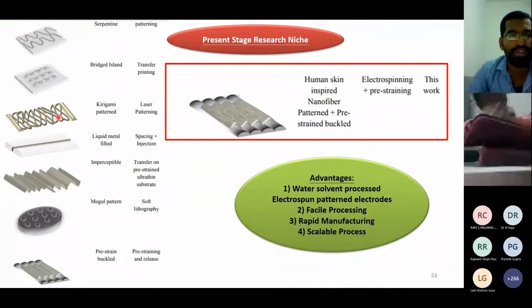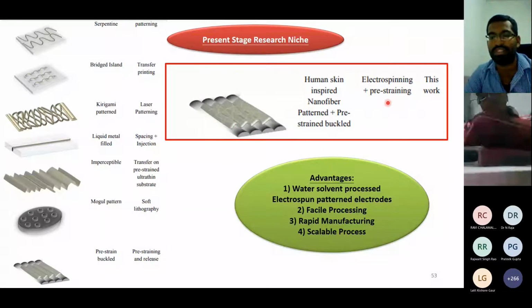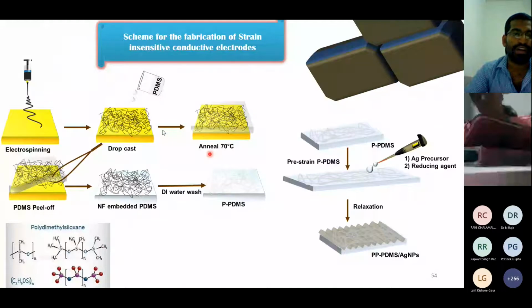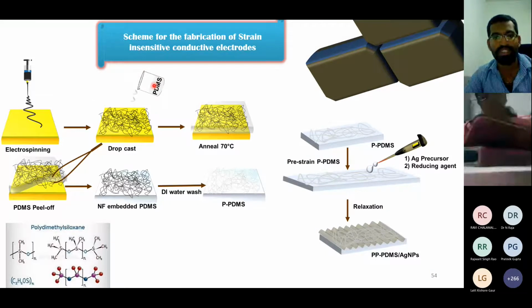And now I want to introduce this kind of patterned structure. Here I'm going to introduce an electrospinning plus pre-straining strategy to form this kind of wrinkled structure, plus having some nano ridges like this. So how do we make this kind of structure? First, we start with our electrospinning method to form 1D structures like this, and then we use some PDMS elastomer, and then we anneal to cure the elastomer. Then you can peel them, and then you can see here there are many fibers getting embedded into your elastomer like this.